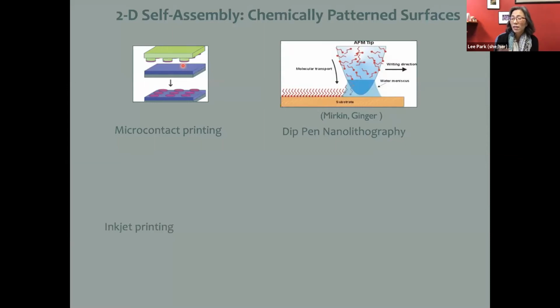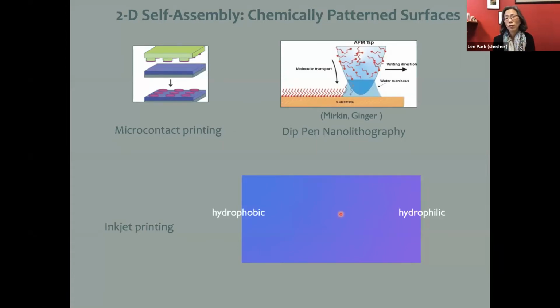We can take these same kinds of molecular inks and load them into an inkjet printer. Just as with any inkjet printer, you can print out a gradient. I've illustrated this here with a gradient from blue to purple. You can load your inkjet printer and print out a hydrophobic to hydrophilic gradient. If you do that, then you have a very smooth transition between a very hydrophobic end of your piece of paper or your substrate and a very hydrophilic end.